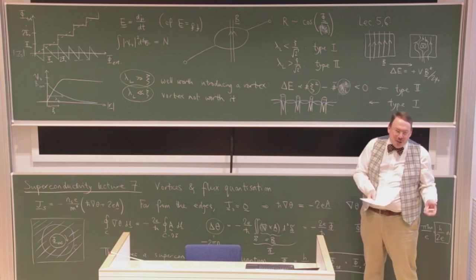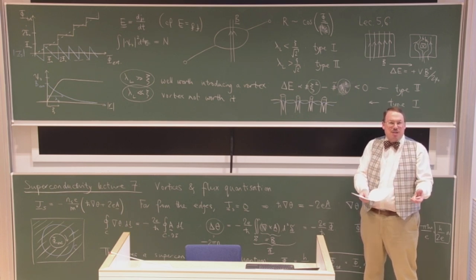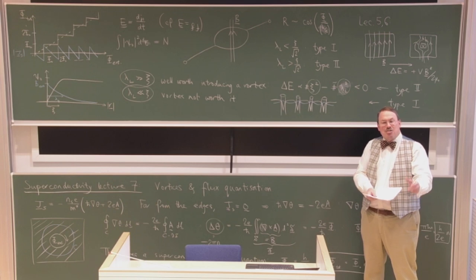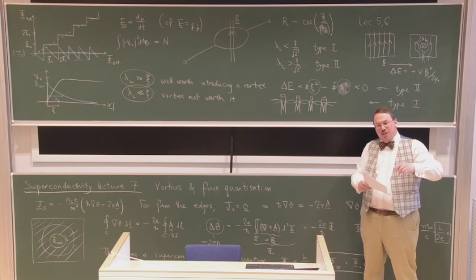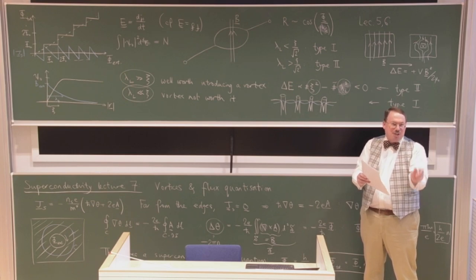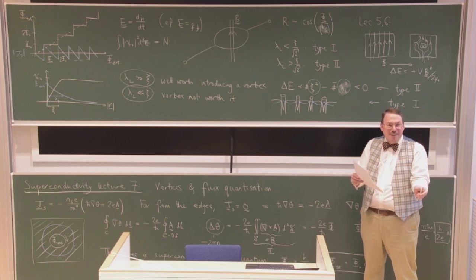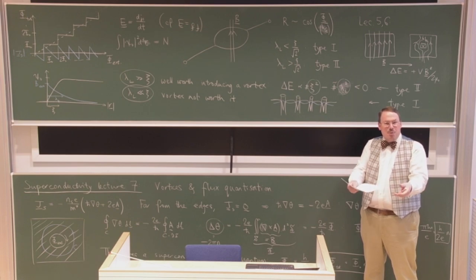But then there are additional complications, like real superconductors are dirty, and so the vortices tend to pin. So actually what you find is that you first have a Meissner phase, then you admit some vortices, but they stick to impurities in the sample, and so they don't flow. And so that sample still superconducts in an electrical transport sense.